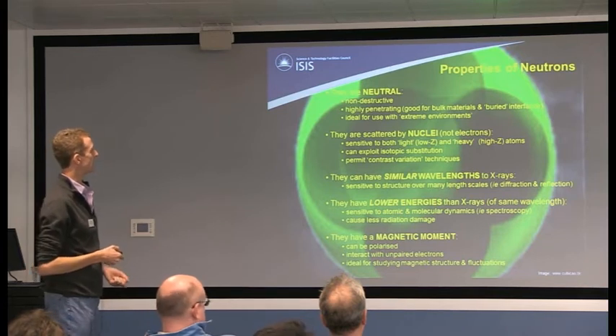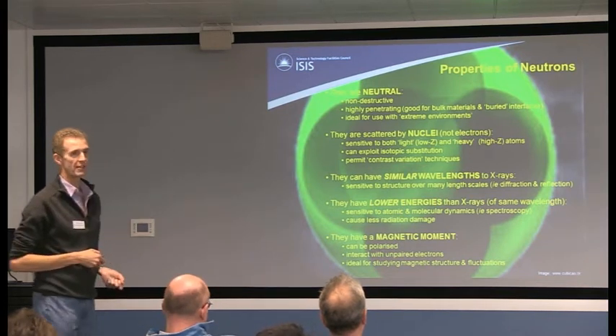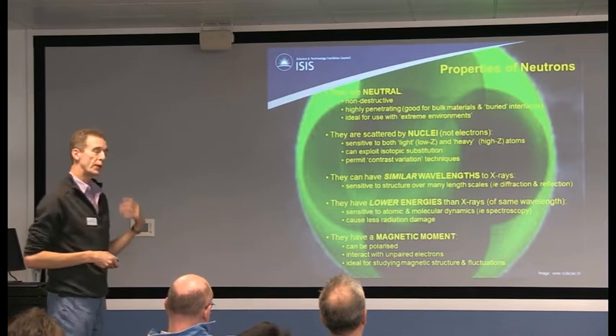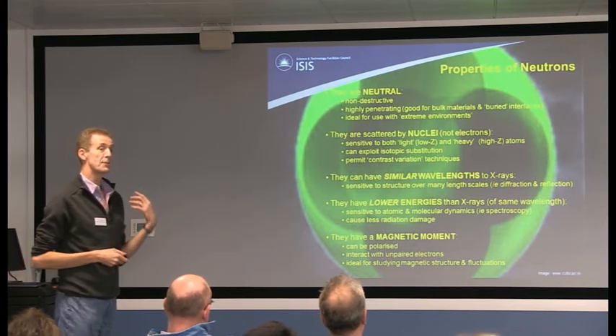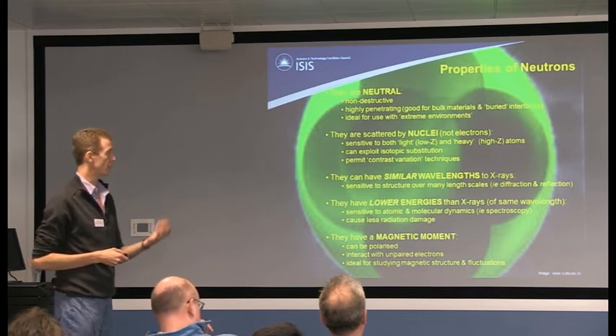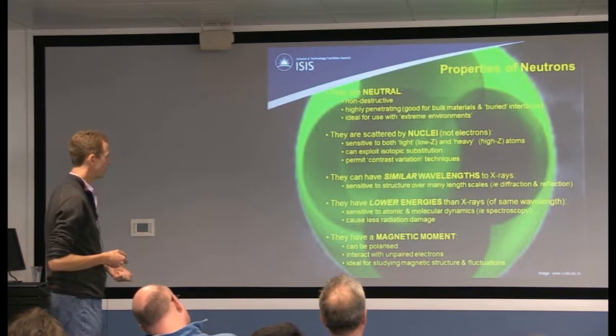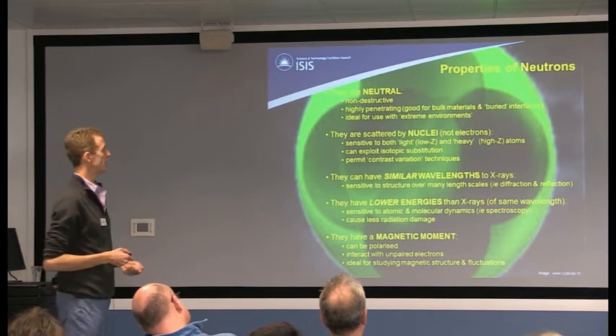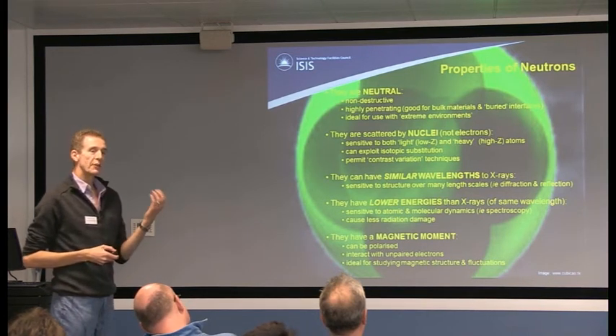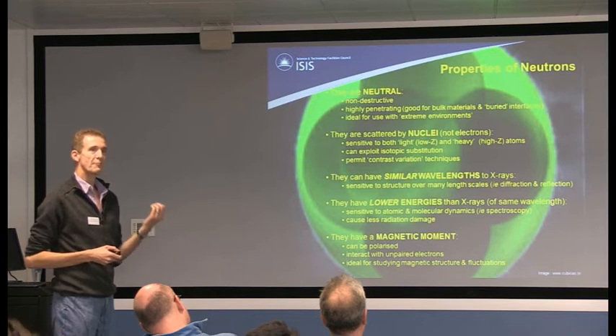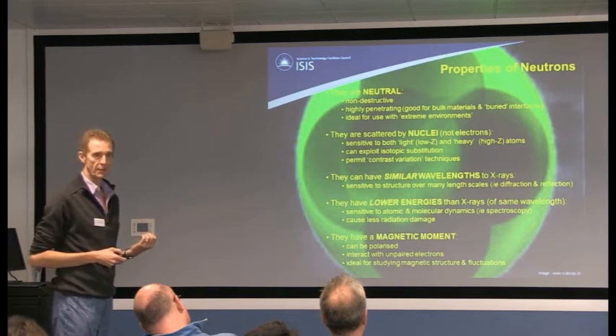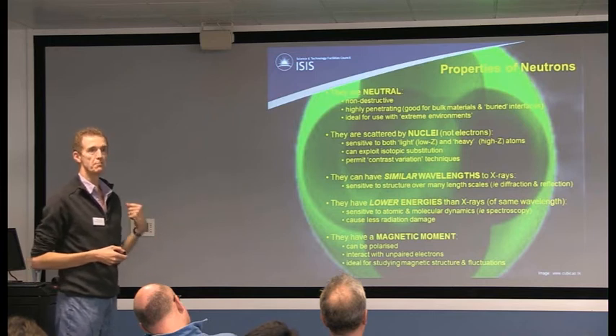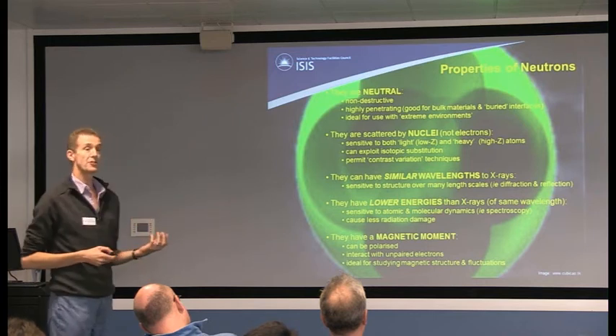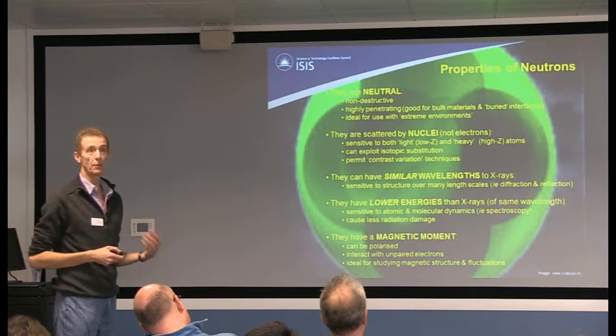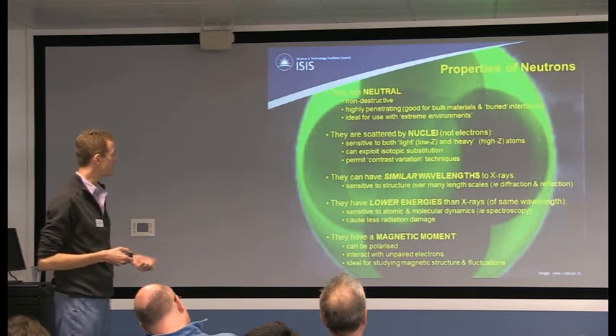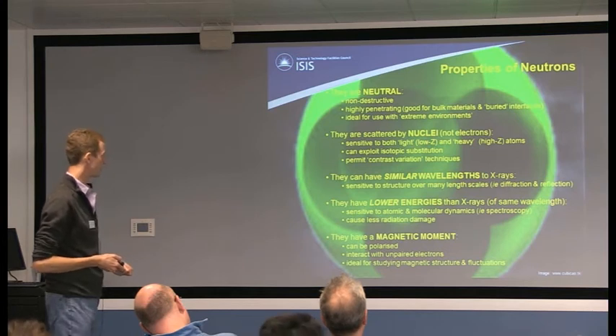Depending on the technique, that may allow you to use something called contrast variation, which I'll come on to in a moment. We can produce our neutrons to have similar wavelengths to the X-rays, for example, that you get here on diamond, as I'll show you in a moment. So that means you can do diffraction type techniques. But for a given wavelength, the neutrons have much lower energies - not thousands of electron volts, but milli-electron volts. That actually means the neutrons are very good for looking at biological material because they're not going to fry it. I'll show you an example of that at the end.